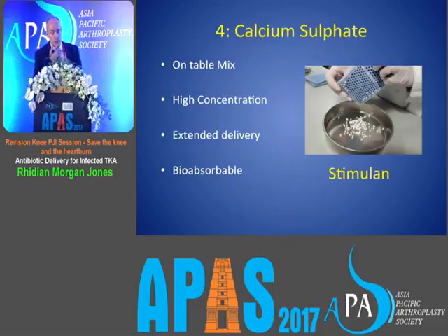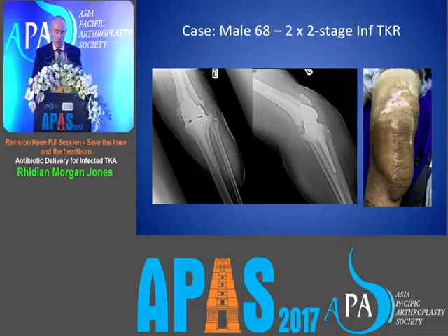Most of my experience recently has been with calcium sulfate, Stimulan. It allows me to mix on the table, at very high concentration, exactly the antibiotics I need. It gives me an extended delivery program of elution, much longer than I get with bone cement, and it's truly bioabsorbable.